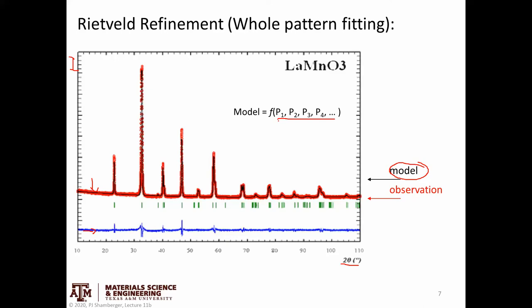Anytime you have a complicated model that's a function of many different parameters, you often can't just hit go and solve for all of those parameters simultaneously. This is ultimately a least squares regression problem where we keep changing parameters individually, and then simultaneously later on, to reduce the overall misfit — calculating terms based on this difference to tell us how well our model fits those observations.